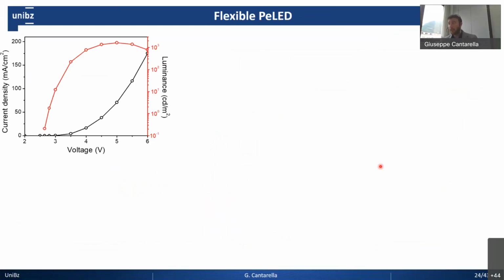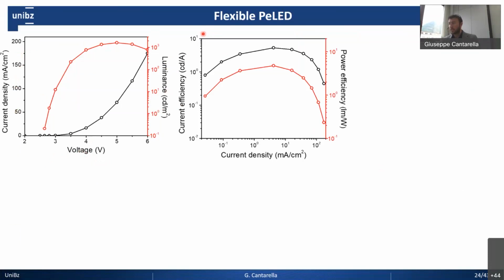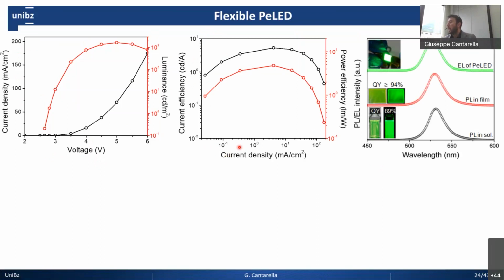We performed the electrical characterization of the LED. So what we did is analyzing the current density and the luminescence as a function of the applied voltage. We also analyzed the current efficiency and the power efficiency of our device as a function of the current density, so according also to the geometry and how big our LEDs were. And the photoluminescence intensity, which is also an advantage with respect to other technology, we compared in colloidal solution, but also in film. And the good thing is that we can have pretty much the same performance at whatever state our perovskite layer is.